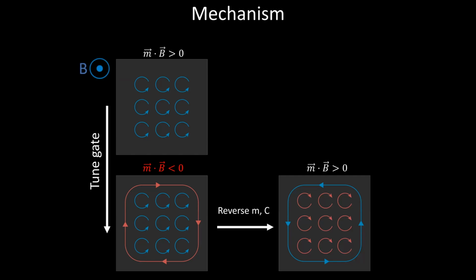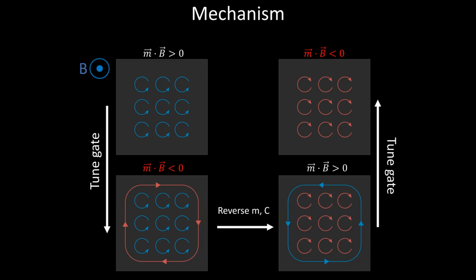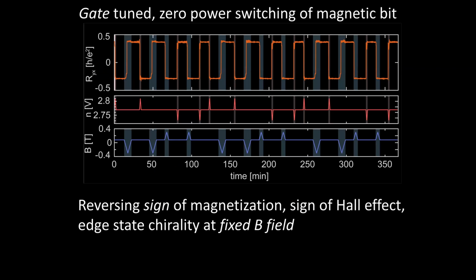But now you switch the sign of the magnetic field, right? And now you switch to the other valley, and then you can tune, sorry, and don't forget about the magnetic field. You switch to the other valley. This is the reversal that occurs when you jump to the other arm of the hysteresis loop. And then as you tune your gate, you now are again no longer in the favored state, and you do this over and over. And so it turns out you can do this over and over again. I call this the world's most expensive magnetic bit because we did it one time. It was a very long running experiment, but you can in fact switch the magnetization, which you can read out through the Hall effect, just by switching an electric field in a capacitor, right?